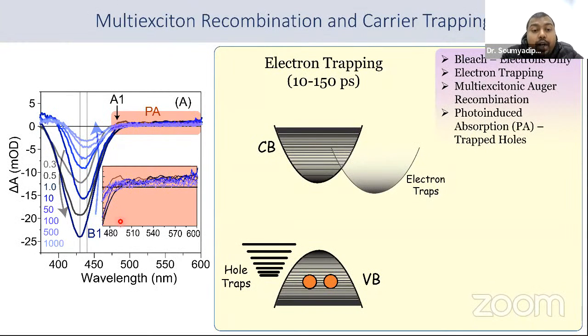Now, what is happening there? Although there are surface traps and other things in water, why are we getting such good emission? Because a 36% quantum yield is frankly very good for water-soluble quantum dots. So what we did was transient absorption spectroscopy. As you can see, this is a pure...